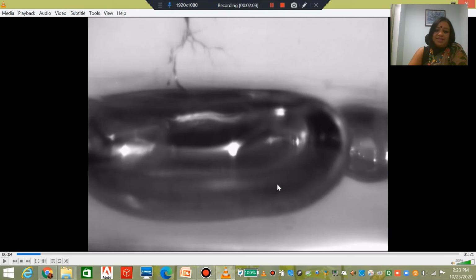But in this case, the void behaves like a barrier between the rest of the electrode material and the ground electrode, and we can concentrate on what is happening on top of the void. What is happening is you have these three channels, and here, as you see this white region, this is where the partial discharge is taking place. So preferentially from there are many filamentary tree channels, but a considerable amount of PD activity is taking place in this tree channel. And you can see what happens next.